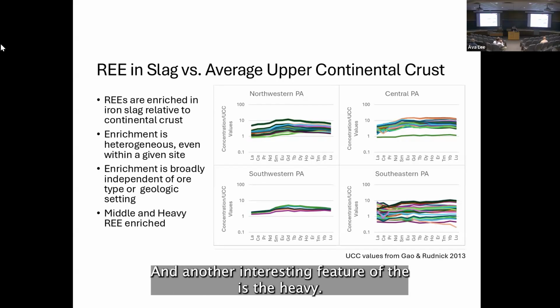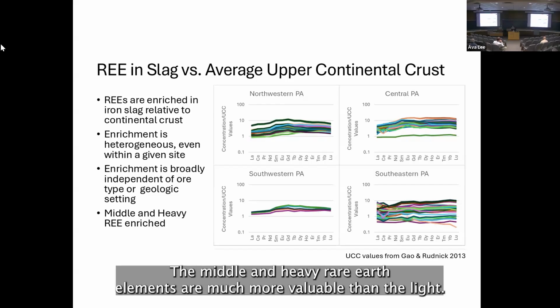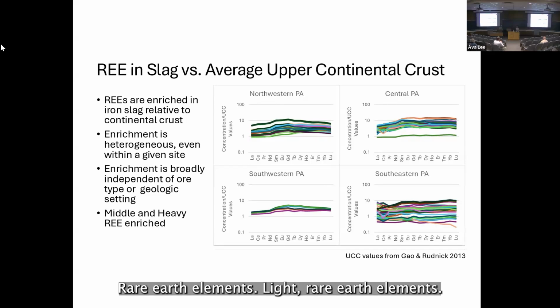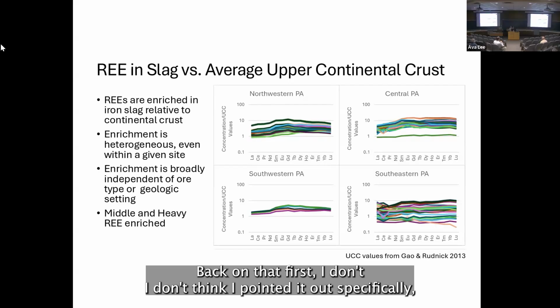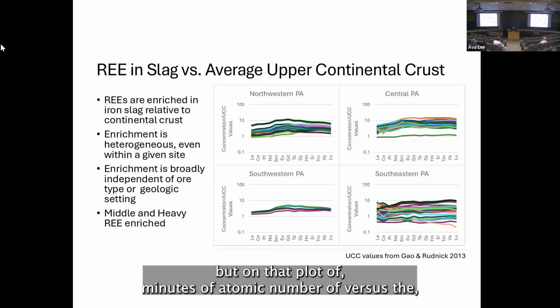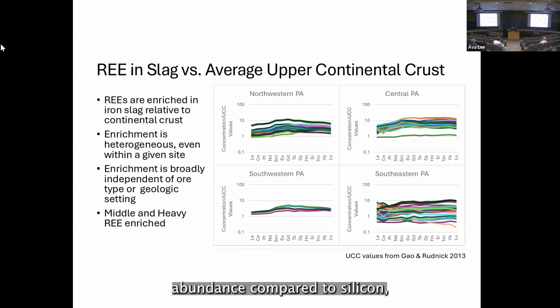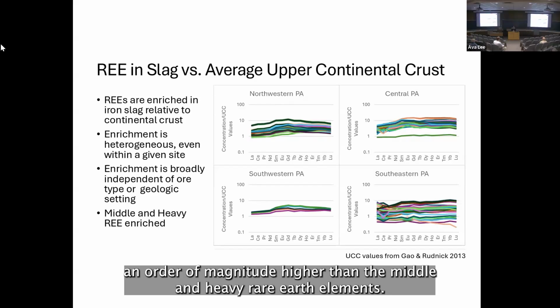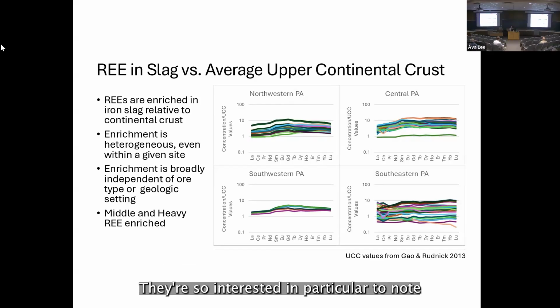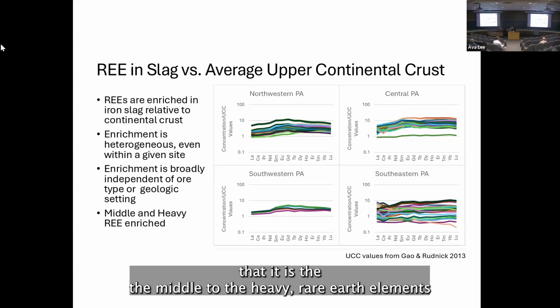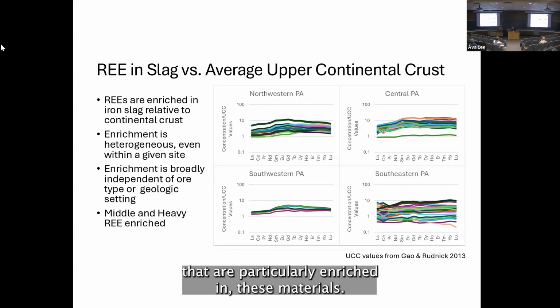And another interesting feature of these, the middle and heavy rare earth elements are much more valuable than the light rare earth elements. Light rare earth elements, back on that first plot, I don't think I pointed it out specifically, of atomic number versus the abundance compared to silicon, the lanthanum, cerium, praseodymium are like half an order of magnitude higher than the middle and heavy rare earth elements there. So interested in particular to note that it is the middle to the heavy rare earth elements that are particularly enriched in these materials.